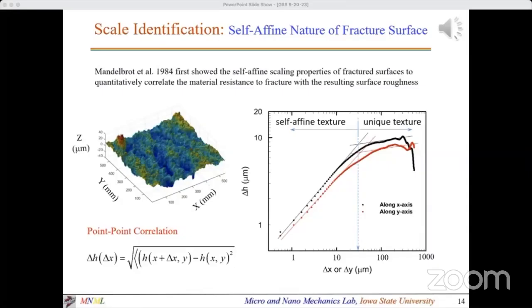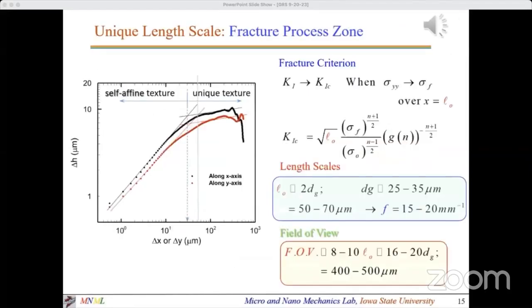Then it deviates and saturates at larger analysis window, which shows the uniqueness of the surface texture. For the example shown here, delta H saturation is at about 50 to 60 micrometer. From fracture mechanics, L0 equals 2 dg, and dg is 25 to 35 micrometer for the examined material. Accordingly, L0 equals 50 to 70 micrometer.